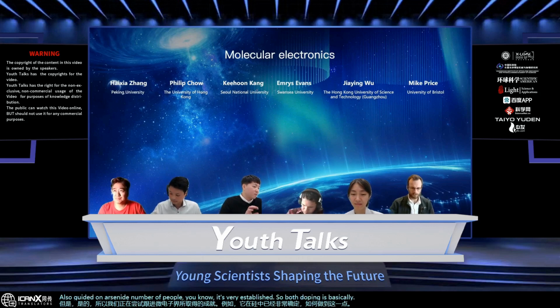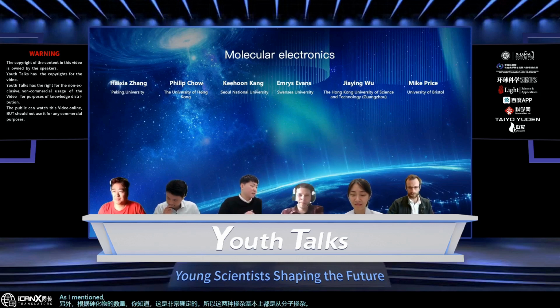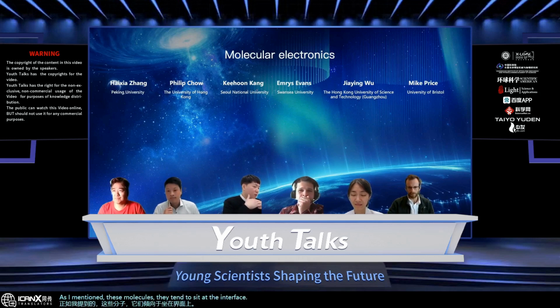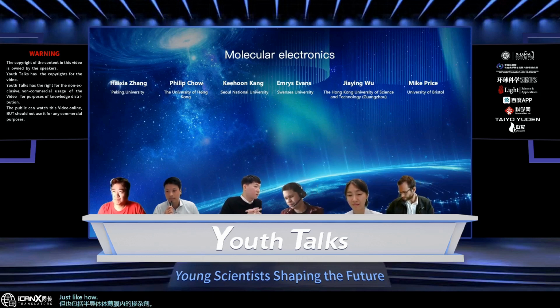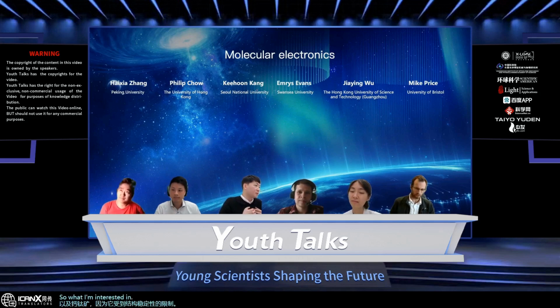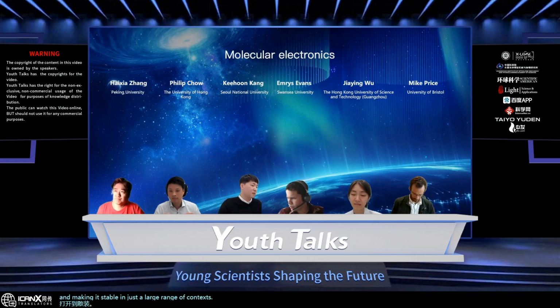It's very established in silicon, for example, how to do that. Also gallium arsenide, it's very established. So bulk doping is basically from the molecular doping perspective. As I mentioned, these molecules tend to sit at the interfaces. And therefore, in order to induce bulk doping, which is not only on the surface, but also including the dopants within the bulk film of the semiconductor, just like how with ion implantation doping, you're able to select the right depth profile for pushing the dopants further into the film of the bulk, which is very difficult for organics, as well as for perovskites, because it's limited by the structural stability. So what I'm interested in is trying to extend this range of doping such that by inducing dopants into the bulk and making it stable, we can induce as large a range of conductivity as well as doping as possible for device applications. Okay, I don't know if that's very clear.